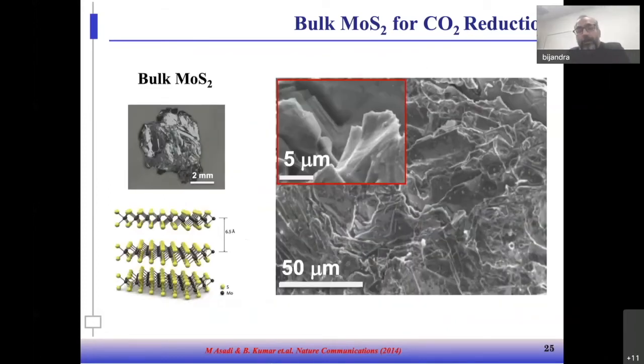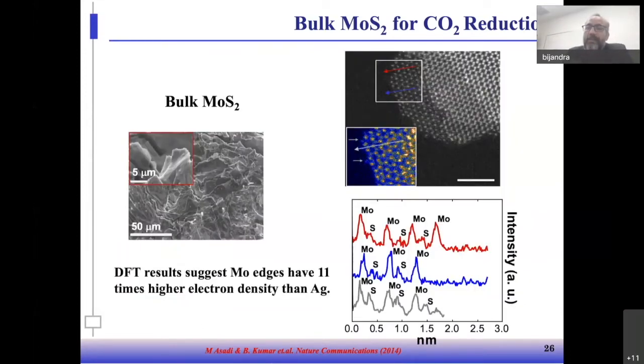So we tried to see really where this catalytic activity is coming from. We have done a lot of characterization. One simple conclusion is that MoS2 has a layered structure. That's the intrinsic property of this TMDC. And when we characterize the edges of this layered structure, they have metal atoms on the edges, in this case molybdenum. And these molybdenum edge atoms have a really high energy density and higher electron density in comparison to silver nanoparticle or bulk silver. So due to higher density and easy exposure to the electrochemical electrolyte, it can perform better